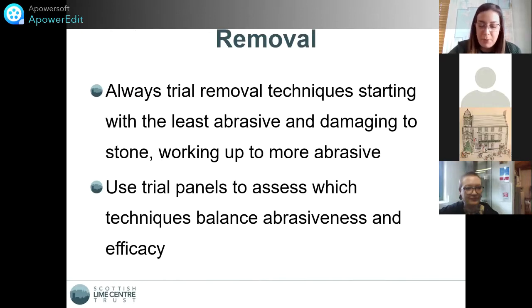For this reason, trials of several techniques and pre-treatments should be carried out to ascertain which is the best and most effective technique, which uses the least abrasive method and the least amount of water. Often overcleaning nowadays actually relates to oversaturation of the stone itself, not just removal of the face of the stone via abrasive techniques, because oversaturation brings salts to the surface of the stone, and that can cause deterioration and salt damage and blowing off the face of the stone over time.